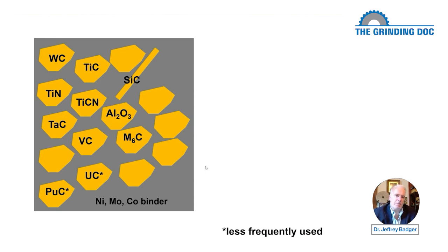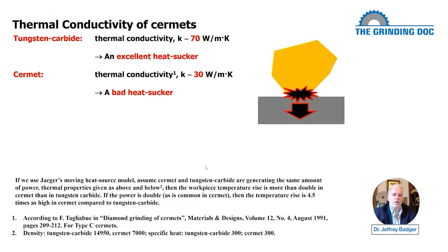And these hard ceramic materials approach the hardness of diamond. They're not quite there, but they're getting closer to the hardness of diamond. So what happens is they dull the diamond grits. Where tungsten carbide does not dull diamond grits, the aluminum oxide, silicon carbide, and other stuff they throw in there does dull the diamond grits. That's reason number one. Reason number two is CERMETs have poor thermal conductivity.